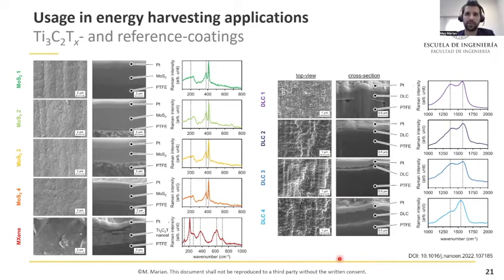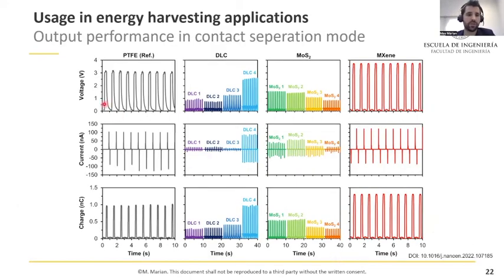we analyzed the triboelectric performance of the TENGs operating in contact separation against aluminum electrodes and also in freestanding sliding mode. And here we can see the voltage, the current, and the charge over time of the PTFE reference, the DLC coated TENGs, the MoS2 coated ones, and the MXene coated ones. And thus we were able to verify that the MXenes outperformed the other films, as well as the PTFE reference in contact separation mode.